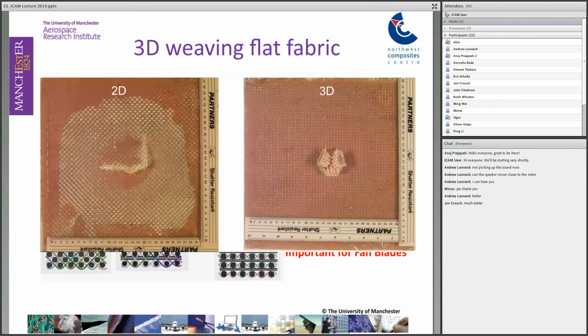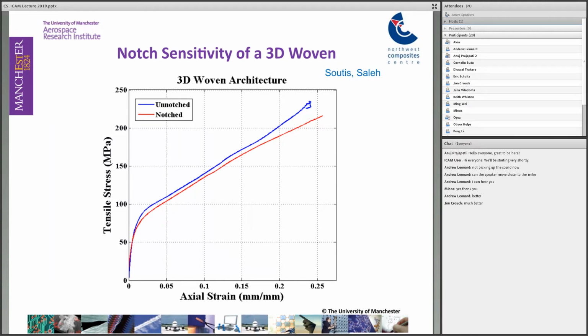Of course, there is very little you can do about the broken fibers. In both cases, we have broken fibers, but we don't have the same amount of delamination as in the two-dimensional fabric. And then, if we look at the tensile behavior of the 3D woven architecture before the damage, before the impact event, and after the damage, which is the red line in our graph, we can see the notch strength of this 3D woven architecture is almost the same, very similar to the undamaged configuration.